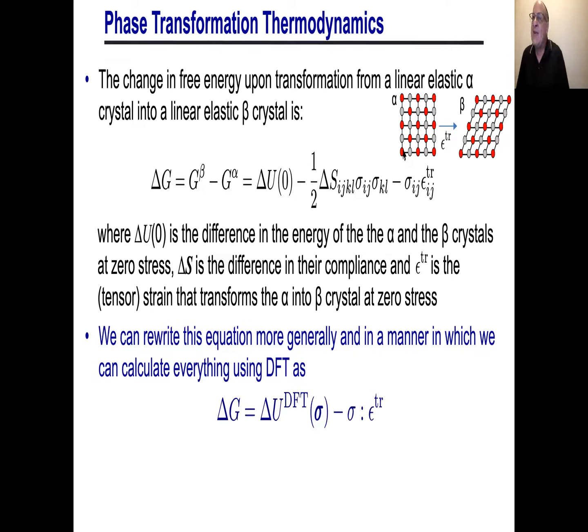Now, as you can imagine, if you're going to be approaching strengths or stress levels which are comparable to the theoretical strength of the material, then linear elasticity is not going to be very good. And so what we're going to have to do is do something beyond that. So what we'll do is calculate the energy of the stressed crystal. We're going to specify the stress. We're going to find the energy of the stressed crystal with DFT. So the way we do it in practice is you figure out what strain you have to apply to get that stress, and then you do the optimization to get the stress, which is your target.